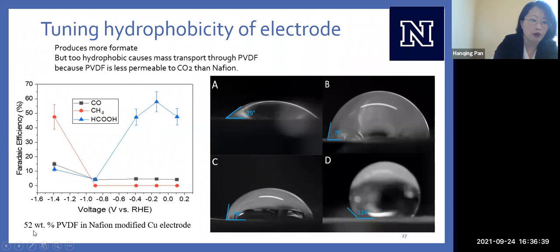But we have to be careful with how much PVDF we're putting into our Nafion. 52% weight percent seems to be the optimal PVDF loading, because too much PVDF will shut down our reaction, as we've seen before, because that's going to cause mass transport problems. Nothing's going to be able to diffuse through. CO2 is not going to be able to diffuse through, because CO2 is a lot less permeable in PVDF than it is in Nafion. And so our optimal PVDF loading is 52%.